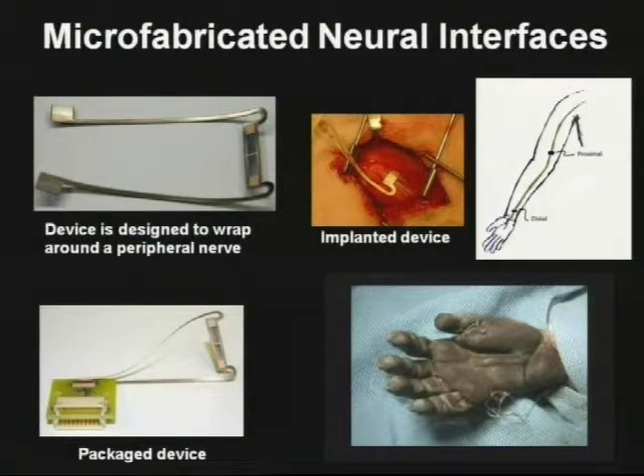And a surgeon would simply wrap the peripheral nerve electrode around the nerve, as shown here, stitch it into place with some simple sutures, and connect it, in this case, since we're still in early development, to an associated PCB that connects you to the necessary electronics to allow for testing of the devices. Now, unfortunately, the movie that I have that sits underneath this picture here isn't running on this computer, but I could show you offline that our devices actually work. We put a stimulating pulse onto this test subject, which was a macaque, and when the pulse is applied, then the hand begins to move.